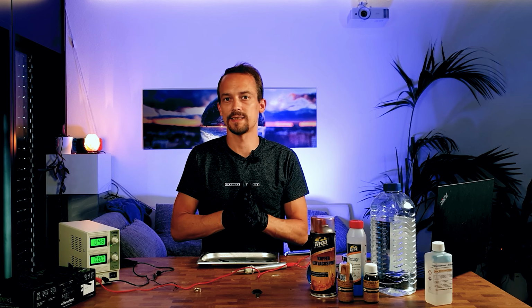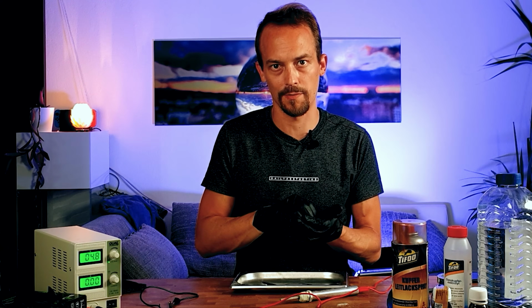So the gold solution you get delivered together with your set is just flash gold. Flash gold means that it's there to basically do a quick surface of gold so you can plate other materials on top of it. It is a very weak and very soft gold, so I wouldn't suggest you use it for your final part. Also, the color and saturation won't be satisfying. I tried using flash gold for this one, and as you can see, the color is not really gold, even though it has a smooth and shiny surface, and I have a lot of black spots on it. So the flash gold is just there to give your next surface something to adhere to.